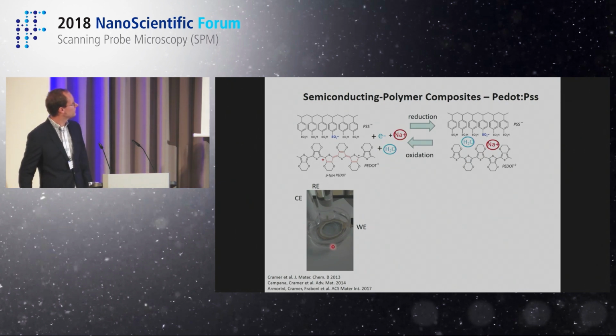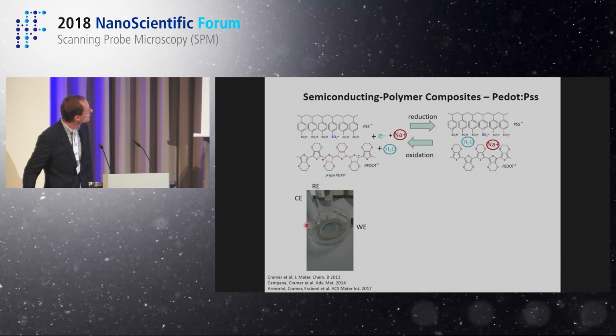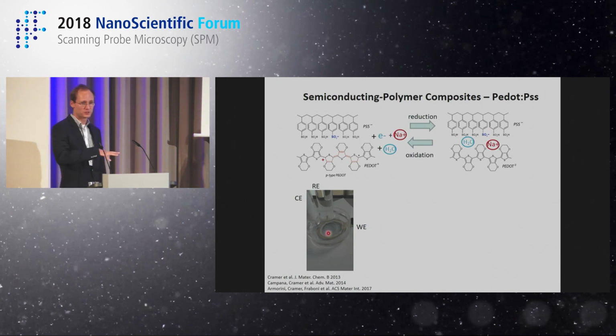Okay, this should be a video, but probably it's not working so nicely. Anyway, it's not very complicated. What you see here is basically one experiment where you can vary the doping. Basically you have a small Petri dish. You have the surface all covered with your semiconducting polymer composite. On top of that, you have a liquid, and then you have the electrochemical setup, which is like a counter and reference electrode in order to control the potential that you apply in the liquid. Of course, you also need to contact your semiconducting polymer composite somehow. That's done with a working electrode.